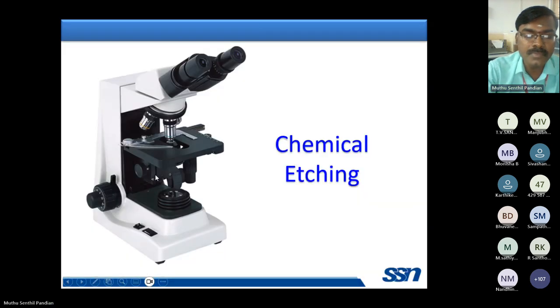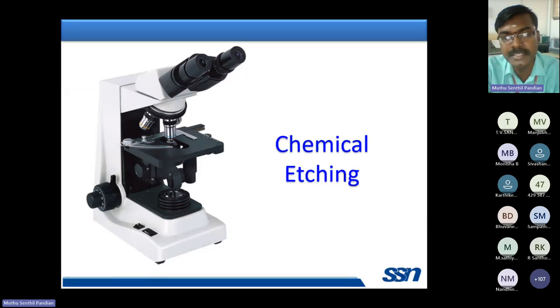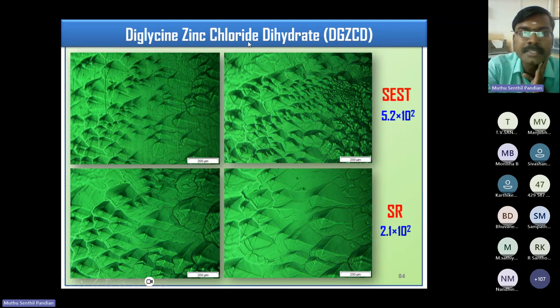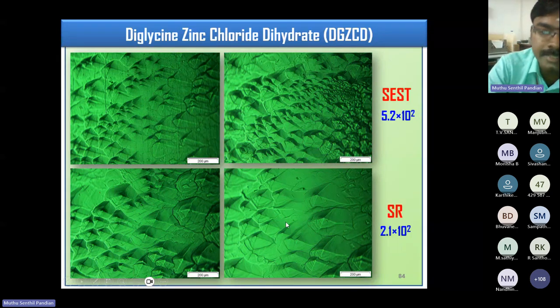Chemical etching is an important and powerful tool to identify the dislocation density of the SEST and SR method grown crystals. This is a diglycine zinc chloride dihydrate single crystal for nonlinear optical application. This is for the conventional method grown crystal, and this is for the SR method grown crystal. You see the number of etch pits in the conventional grown crystal is more because of the grain boundaries, but in the SR grown crystal it is less. The approximate etch pit density of the conventional grown crystal is 5.2 × 10² cm⁻², but in the SR method grown crystal it is very much less, because there are no grain boundaries in the SR method grown crystal.